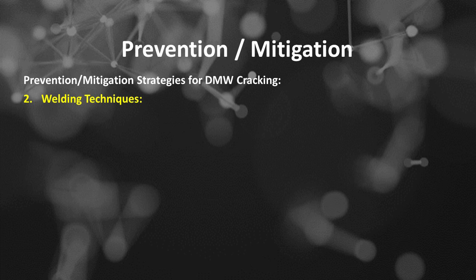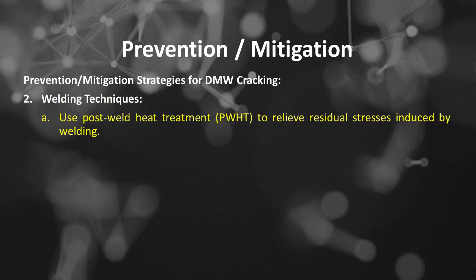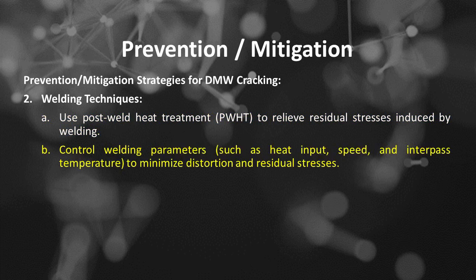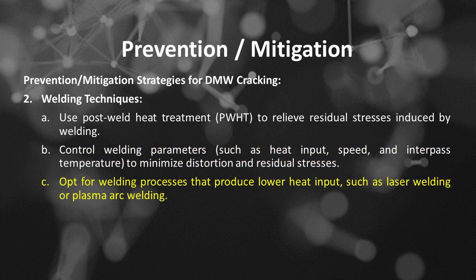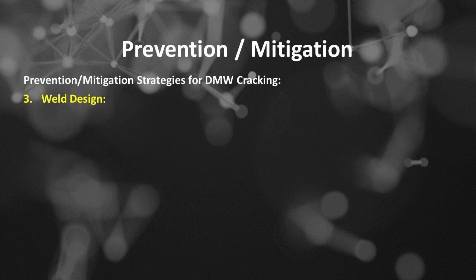Include: the first is use post-weld heat treatment, or PWHT, to relieve residual stresses induced by welding. The second is control welding parameters, such as heat input, speed, and interpass temperature, to minimize distortion and residual stresses. The third is opt for welding processes that produce lower heat input, such as laser welding or plasma arc welding. Number 3 is weld design.